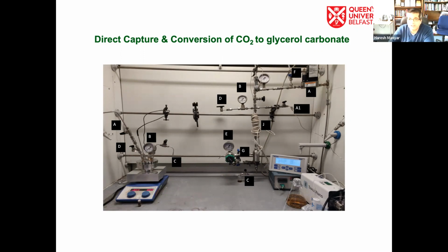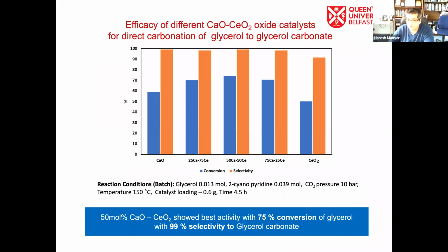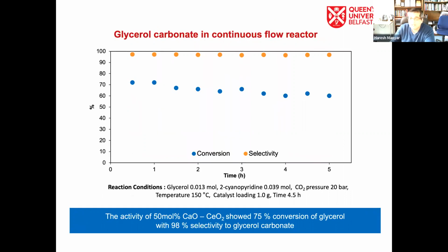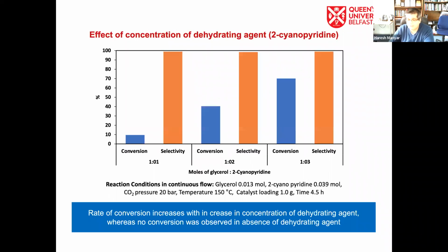In this particular study, we used direct capture and conversion of CO2 to glycerol carbonate. We again optimized the composition of the materials, and we can see that a 50-50 mix by weight of calcium oxide and cerium oxide showed the best conversion and selectivity to glycerol carbonate. The robustness of the materials was tested in the continuous flow reactors. Again, you can see a very nice steady state performance, with high selectivity and high conversion achieved per pass in the continuous flow reactors. Sometimes flow reactors have their own advantages over the traditional batch reactor. You can definitely improve the productivity.